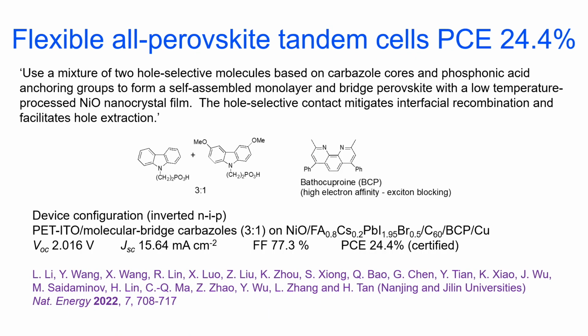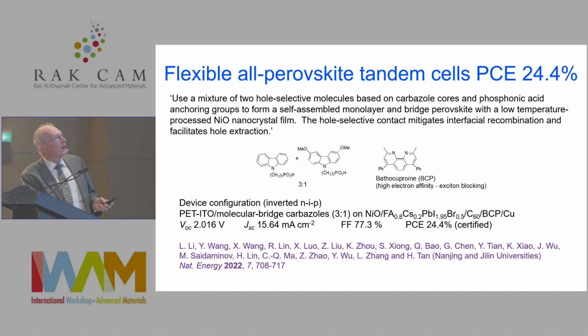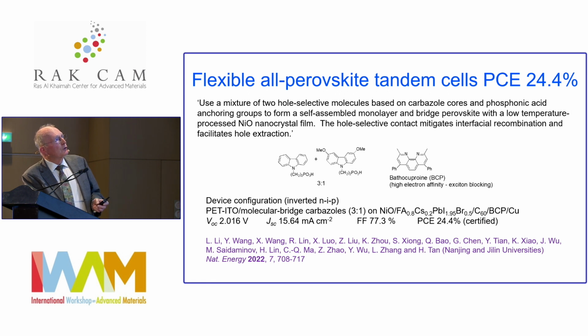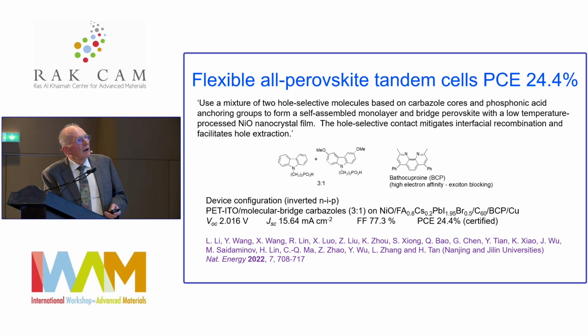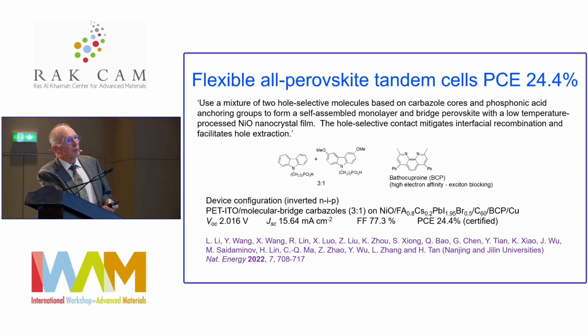And then a comparable result was a flexible all-perovskite tandem cell with a small area, not a large area, obtained by this group. They used two hole selective materials based on these carbazole structures to give a self-assembled monolayer, and they bridge the perovskite with a low-temperature processed nickel oxide nanocrystal film. And then the hole selective contact mitigates interfacial recombination and facilitates hole extraction.